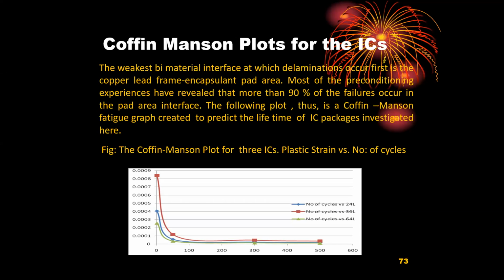When we plot plastic strain versus the number of cycles, it's not an SN plot, it's different from an SN plot. And we find that the plastic strain severely comes down even after, say, about 50, 100 cycles of normal use. Normal use is 1 to 5 cycles a day. So we find that even after 100 cycles, the plastic strain is severely reduced because fatigue normally makes a material a lot embrittled, and then it sucks off a lot of plastic strain.